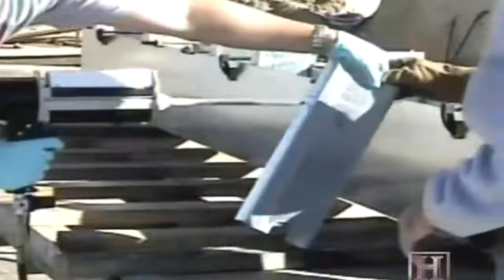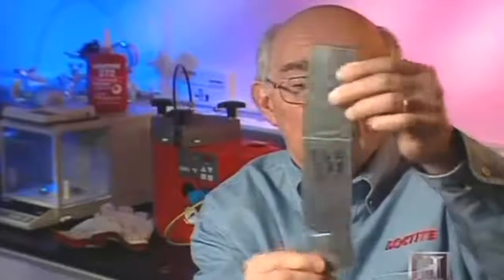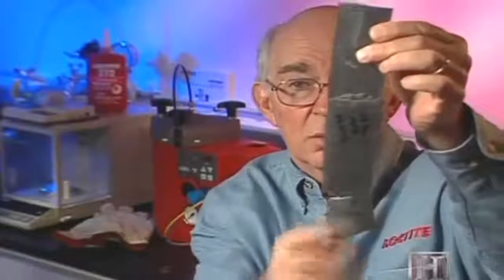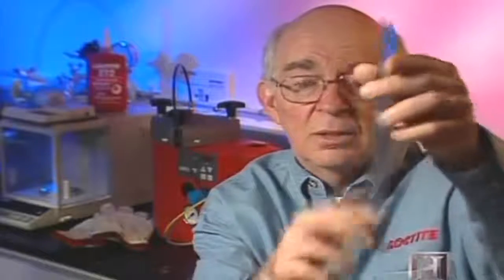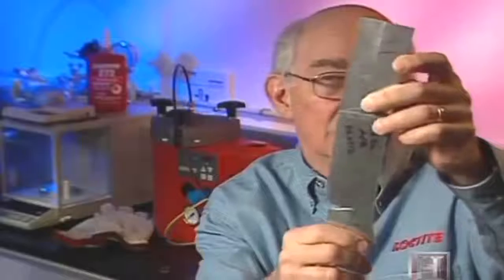This is 16-gauge steel, okay? And look what we've done to the 16-gauge steel. The adhesive is completely intact. Look what we've done to the steel. We've actually ripped the steel. And this happens at about 5,200 to 6,000 pounds.